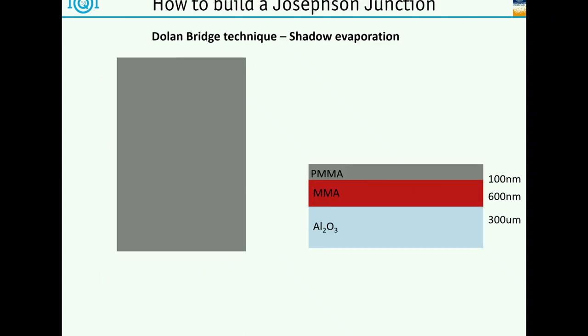So what you see here is the side view of a sapphire wafer, so something typically like 300 micron thick. Obviously this picture is not to scale. Then on top of that, we put a so-called e-beam resist. This is a polymer which reacts to electrons. So of about 600 nanometers here, and another layer of a different polymer of about 100 nanometers. And this is the same chip from the top with those two layers. So all we see is this gray top layer.